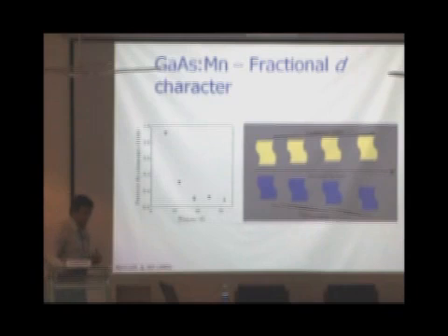The thing is that it's because of the d orbitals that are present. It's the d orbitals that are present in the highest occupied levels, in the valence bands. They contribute to the half metallic character. And what happens as you keep coming down in size?